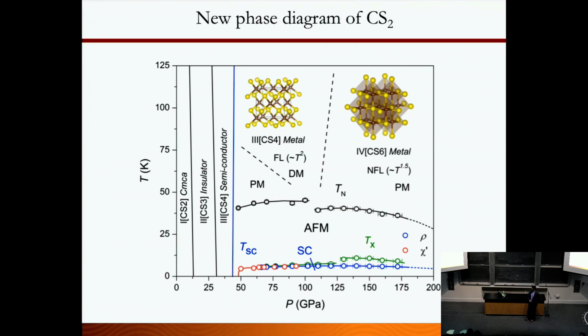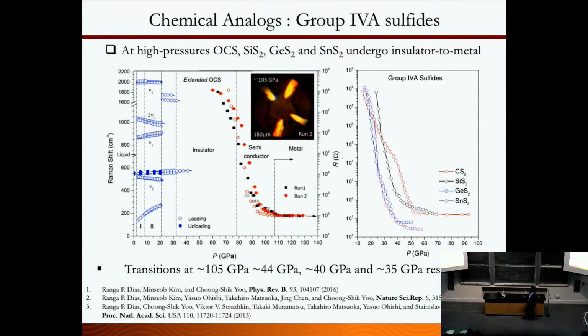We haven't really tested that one. So if I summarize the new phase diagram of carbon disulfide, it goes from an insulator to metal transition, and which I haven't shown you here, it also goes through a magnetic transition, an antiferromagnetic transition, before it goes to a superconducting transition. So it has a superconducting and antiferromagnetic transition, and it goes from 4-fold to 6-fold coordination under pressure.